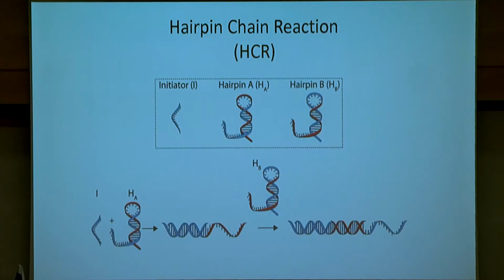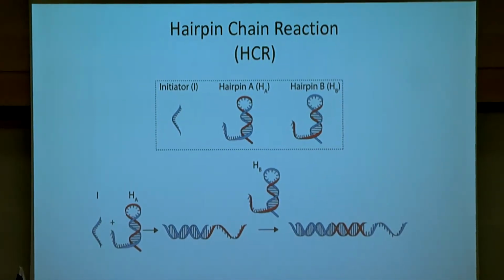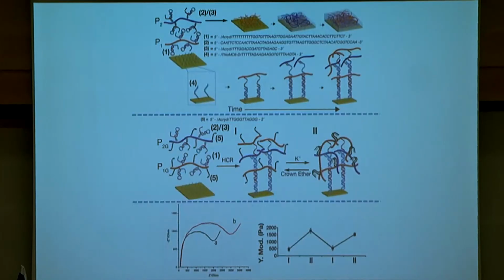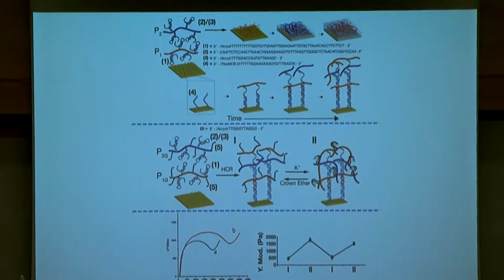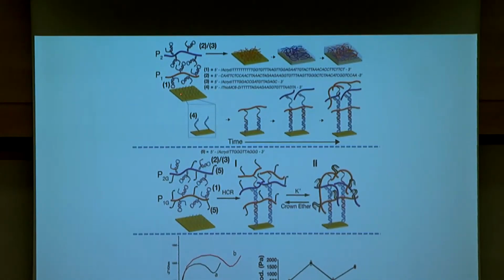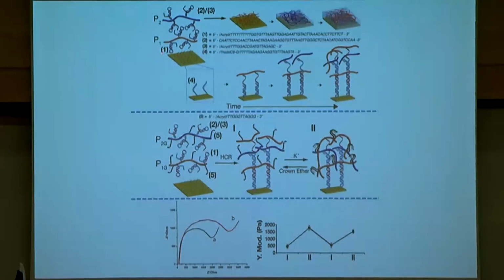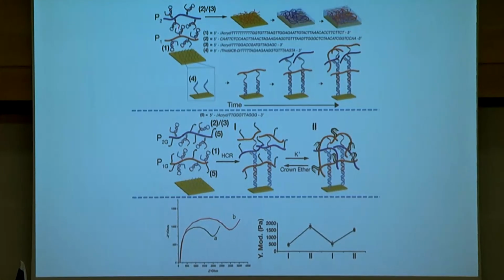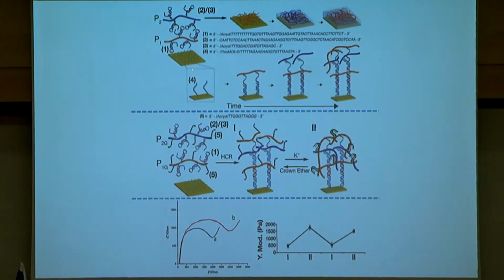This concept was developed by Pierce and Dirks, and we adopted it to develop the deposition method to deposit hydrogels on electrode surfaces. And here I want to show you first the concept. The concept is to immobilize a promoter unit on an electrode surface, for example, a gold surface, and to take polymer chains of acrylamide, a monomer that is modified with two hairpins of DNA. Once we interact these two types of chains with the promoter, we induce the hybridization chain reaction that I just described, and we get a duplex-bridged hydrogel on the electrode. This is a film that is on the electrode.